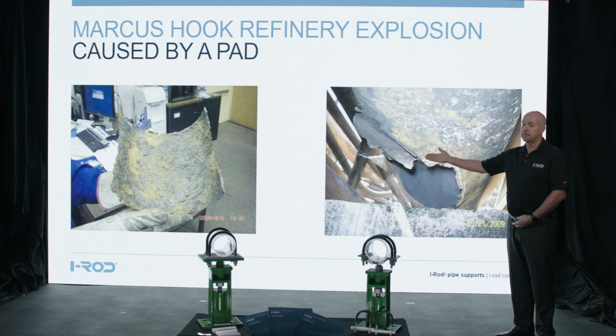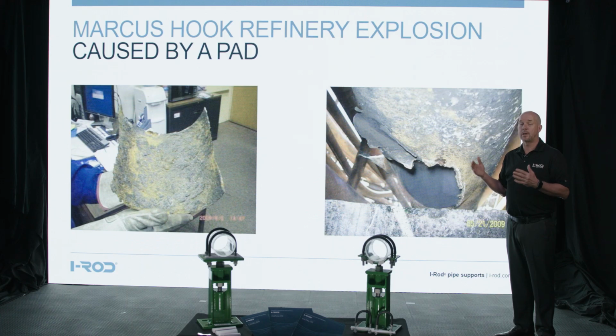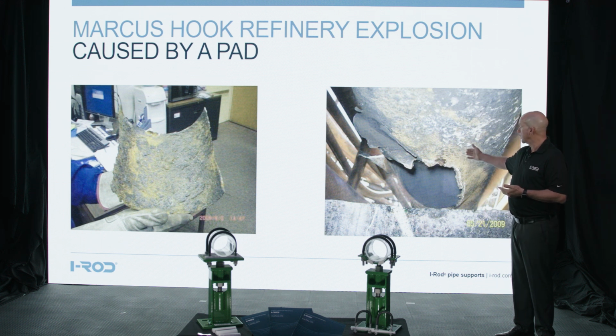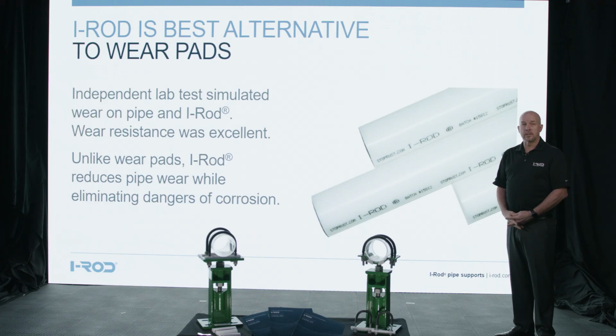They had a curved metal pad that was installed underneath the steel pipe. They were having some damage from the pipe moving around. They wanted to stop the pipe from rubbing against the support, so they thought if we just put a curved metal pad in between, then the curved pad will take the damage as opposed to the pipe. The problem is moisture got into that curved area and held it against the pipe. You'll notice here on the right, this is an 8-inch high-pressure gas line. It only took a small pinhole leak of that gas, ignition source close by, ignited the gas and blew up their plant.